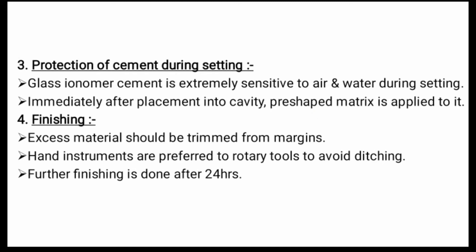For finishing the glass ionomer cement restoration, excessive material should be trimmed from the margins. Hand instruments are preferred over rotary instruments to avoid ditching. Further finishing is done after 24 hours. Before dismissing the patient, the restoration is coated with a protective agent to protect the trimmed area, as failure to protect for the first 24 hours results in a weakened cement.